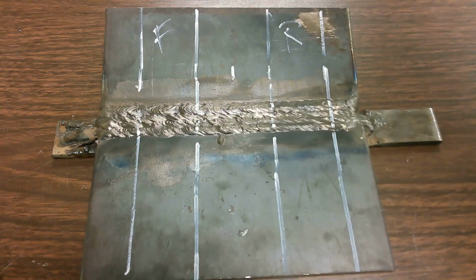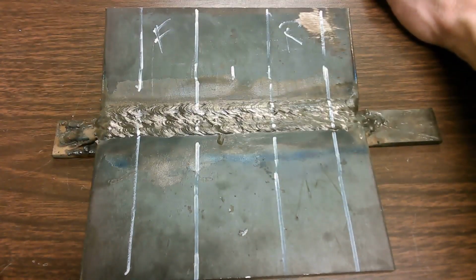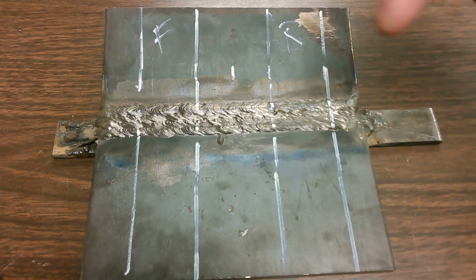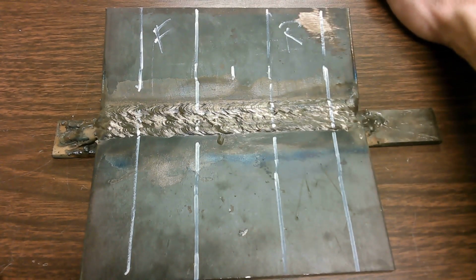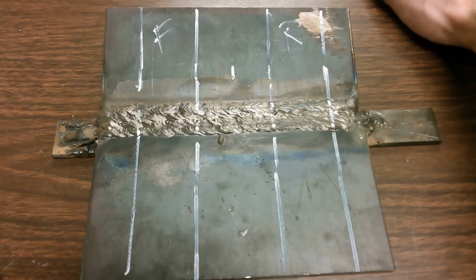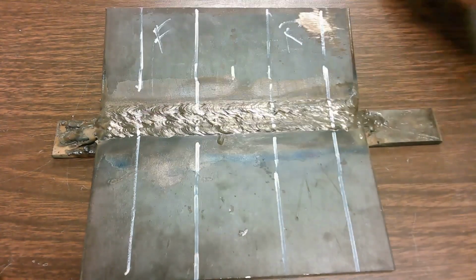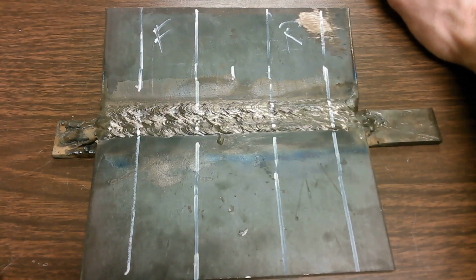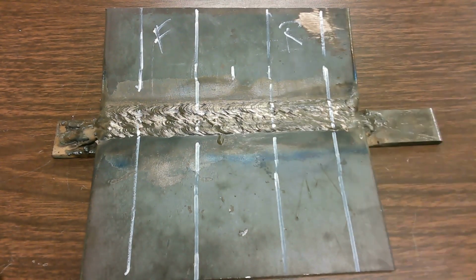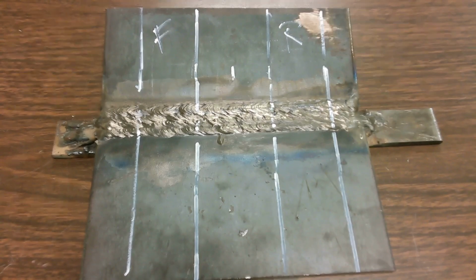So what we're going to do is cut these strips out with our horizontal bandsaw. There's a little trick to it, depending on what saw you have. You could cut it with a vertical bandsaw, but I'm going to show you how we set up our horizontal bandsaw to do this. After we get the strips cut, then we're going to tip it up and cut the backing strip off with a torch. Some people cut it off ahead of time. It's just a lot more torch work. You've got 7 inches of backing strip to remove versus 1.5 inches and 1.5 inches. So I like to cut the backing strips out afterwards, which is another reason why I like to cut it out with a saw, so that you don't have that extra thickness to deal with. So let's go cut it on the saw.